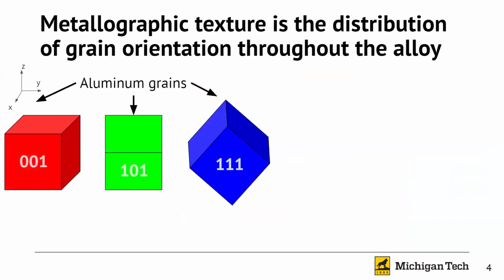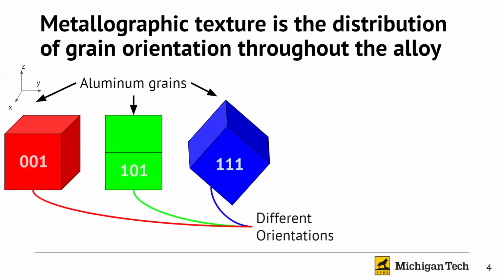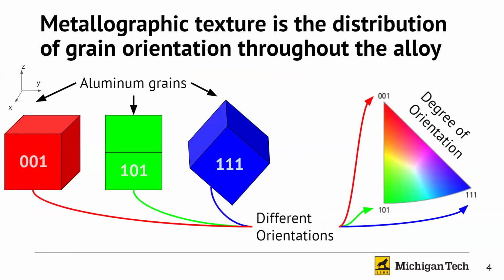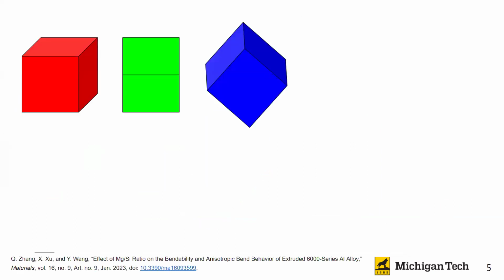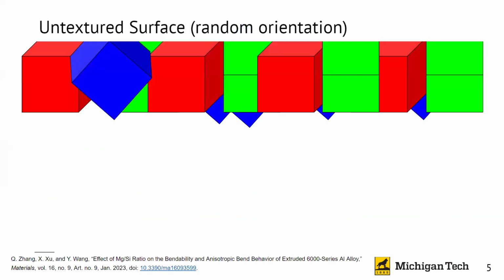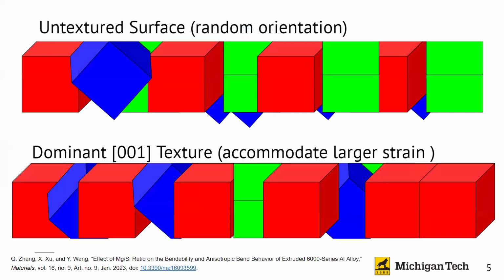Extrusion influences the texture of 6005A aluminum. The texture is the distribution of grain orientation. There are 001, 101, and 111 crystal orientations, and every orientation in between. These grains make up a distribution of organized grains to make texture. We are looking to get more 001 texture to accommodate larger strains for side impacts.